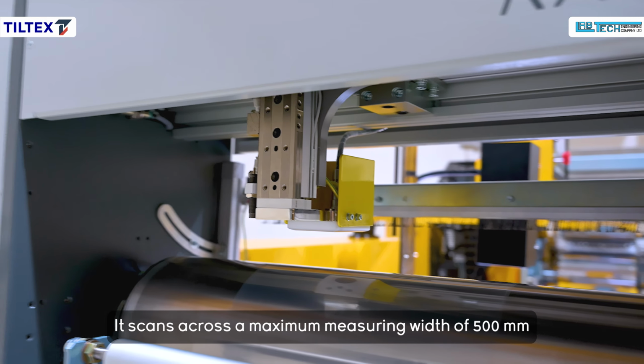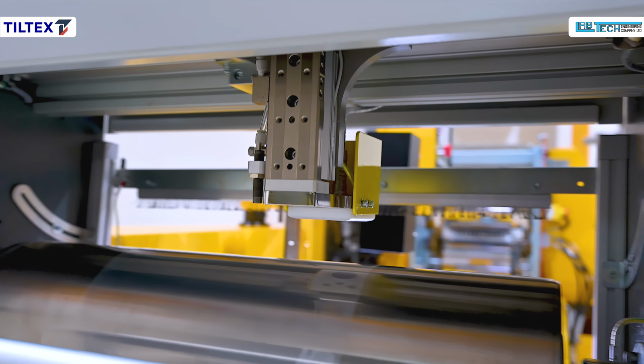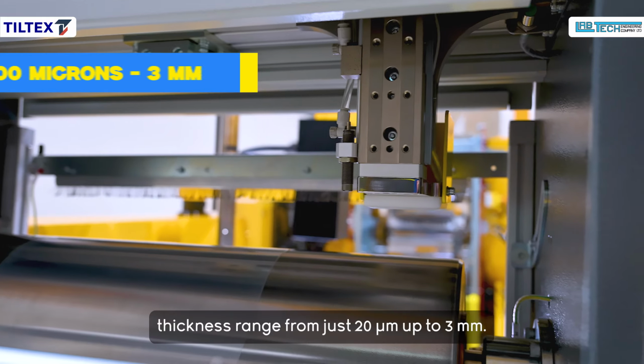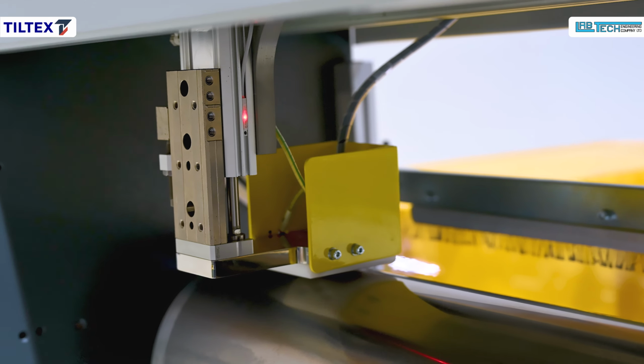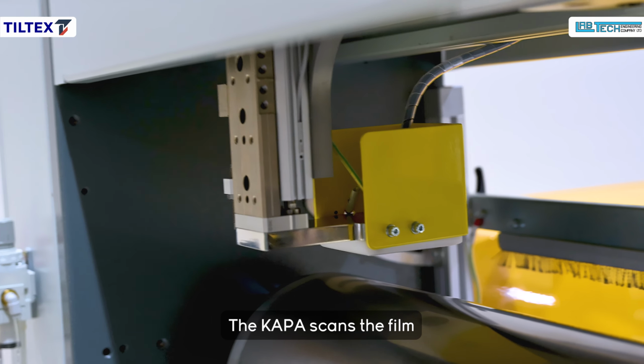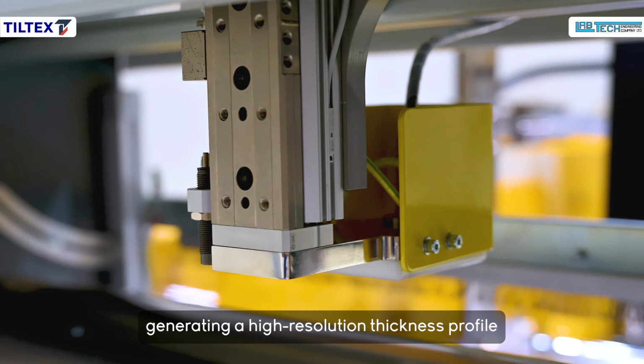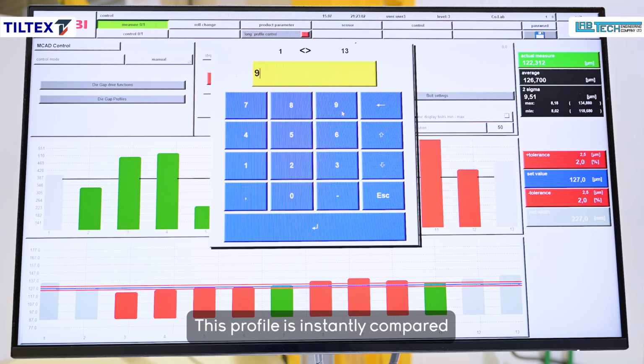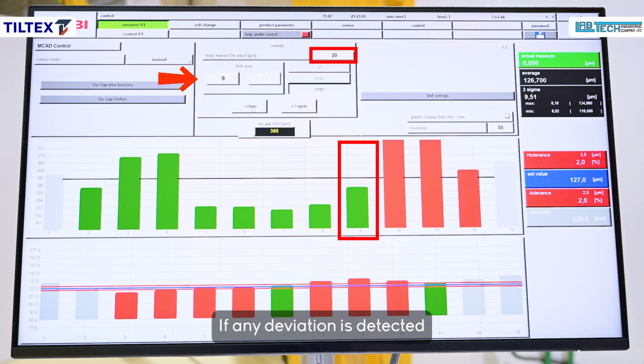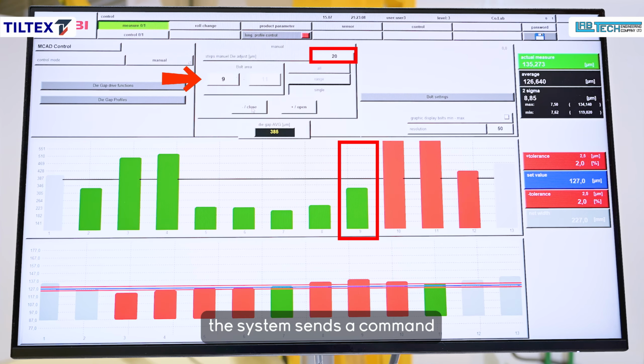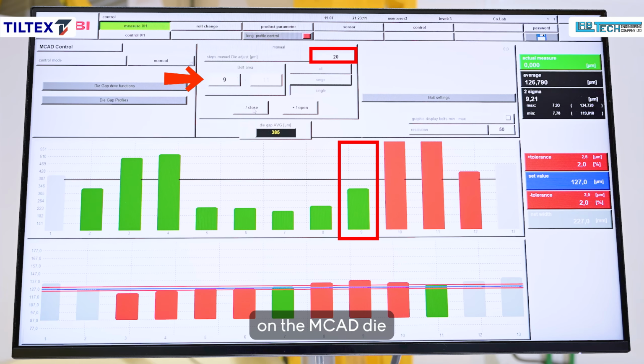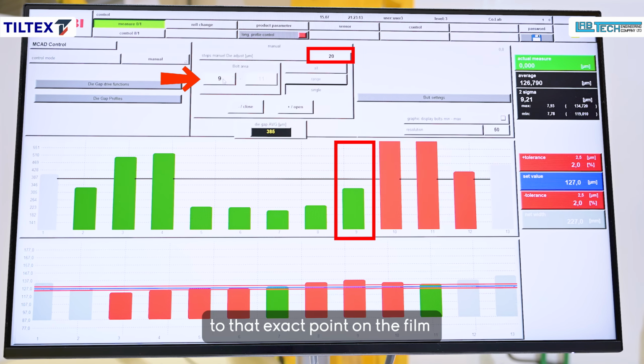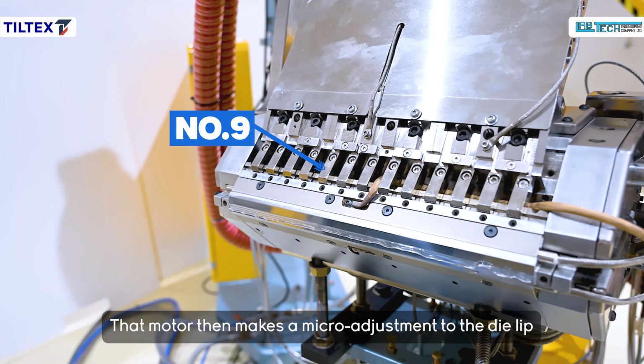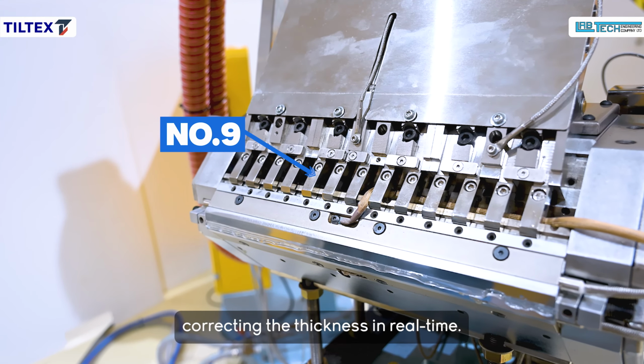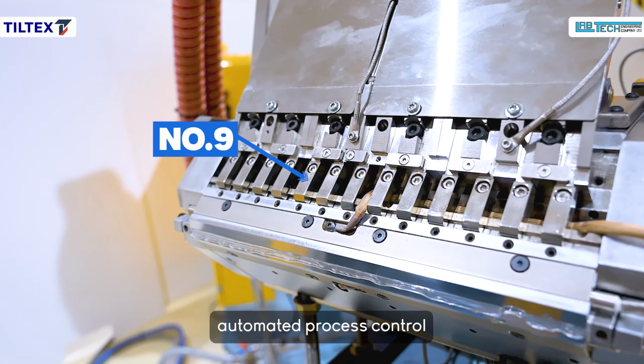It scans across a maximum measuring width of 500 millimeters, accommodating a film thickness range from just 20 microns up to 3 millimeters. The Kappa and the MCAD die work together in a continuous feedback loop. The Kappa scans the film, generating a high-resolution thickness profile. This profile is instantly compared to your desired set point. If any deviation is detected, the system sends a command to the specific stepper motor on the MCAD die corresponding to that exact point on the film. That motor then makes a micro adjustment to the die lip, correcting the thickness in real time. This is true, hands-off, automated process control.